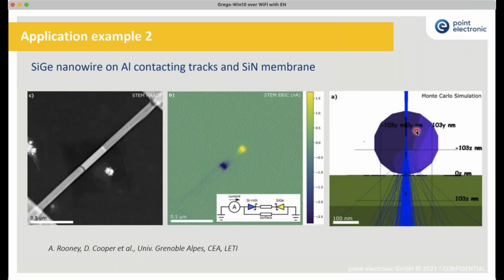And that's the power of EBIC. At the same time as you manage to image HAADF, you can also image EBIC. And in the EBIC, we immediately get two peaks, two spots. And because we know the relationship with the current, we know that one of them is positive and one of them is negative. So one is bright and one is dark. And they are colored here in pseudo-color just to make it easier to look at. And because we see these two regions, we know we have two fields. That's what EBIC does. It shows us where the fields are.